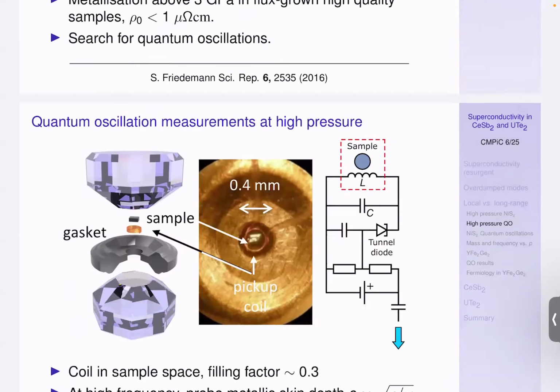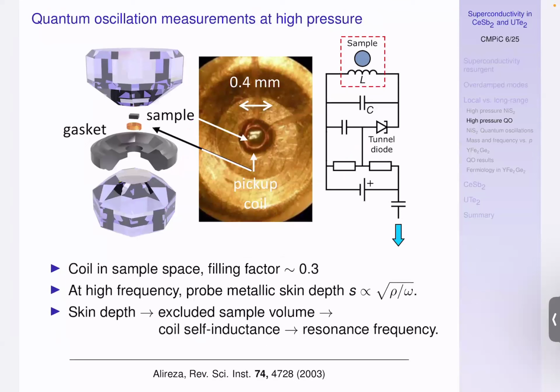But it's a tricky experiment to search for quantum oscillations under pressure, because you need to put your sample inside one of these tricky anvil cells, and the samples are tiny, 0.1 millimeter, maybe 0.2 millimeters. The way we do it is put a little pickup coil around the sample and make that part of a resonance circuit, an LC resonance circuit. And then we measure the resonance frequency of that circuit. We call it TDO because the so-called tunnel diode is used to drive the resonance. But that's technically very important, but conceptually unimportant.